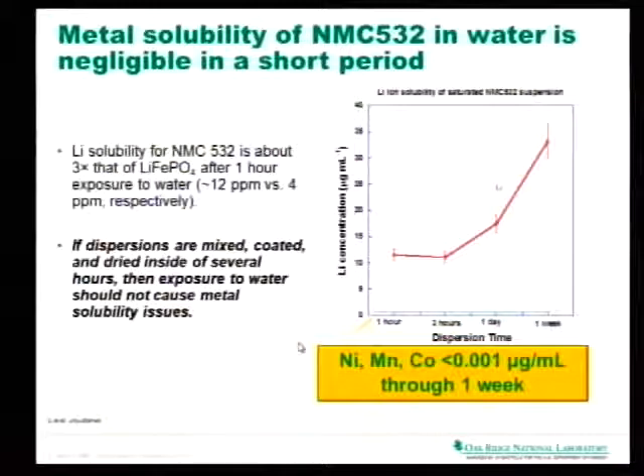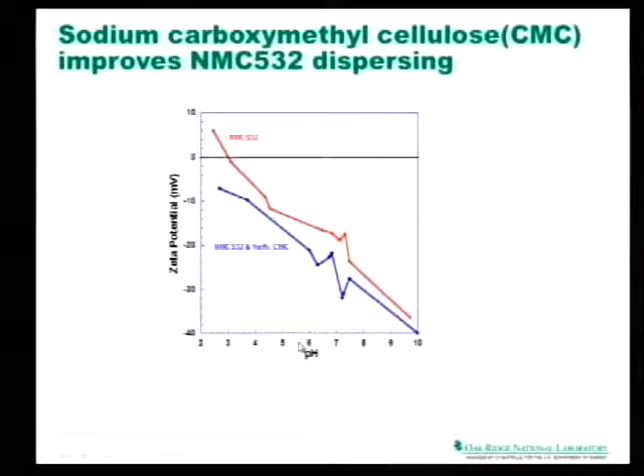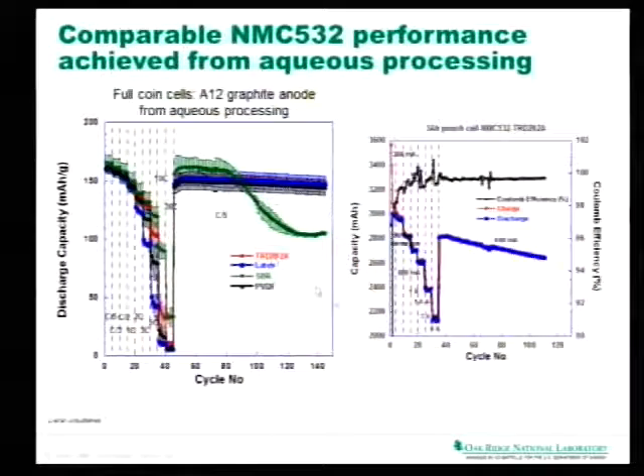All we need to do is develop our dispersion chemistry again, make sure our material wets it, and we're good to go. So this is the Zeta potential again. You see again that red curve is that unstable Zeta potential where you have some crossing over into zero. When we add our dispersion to it, then we're able to move that curve down and improve it dramatically.